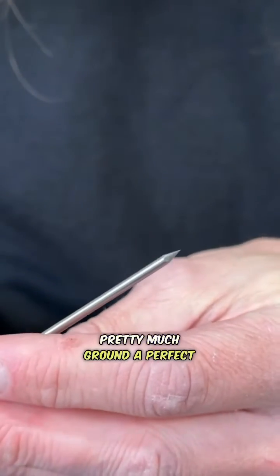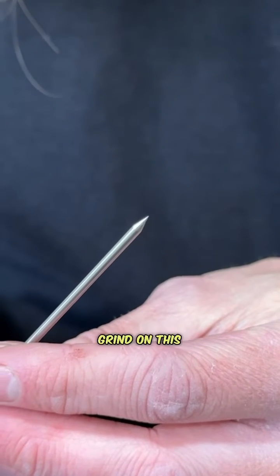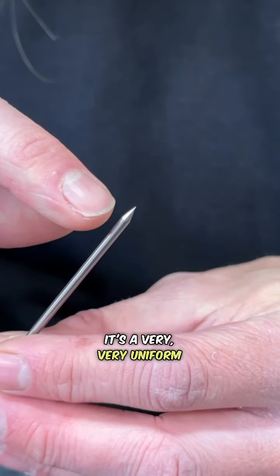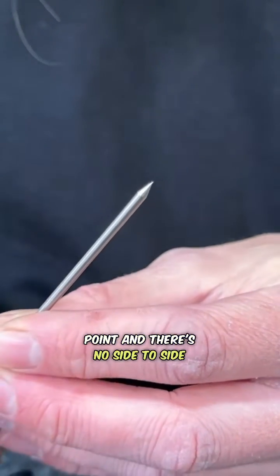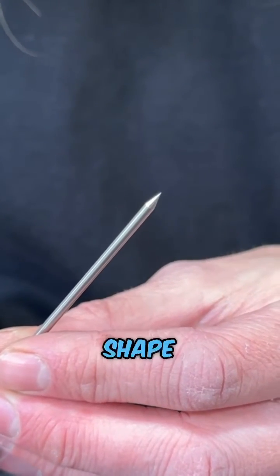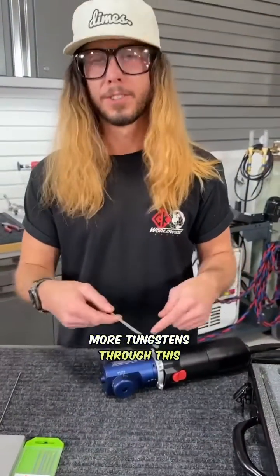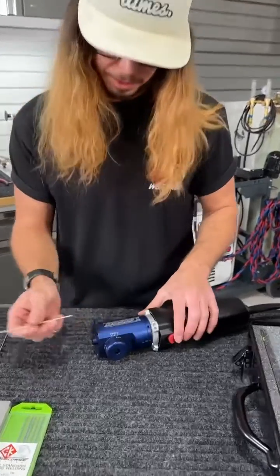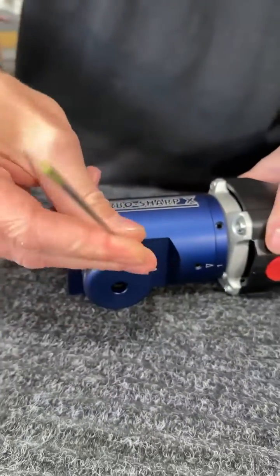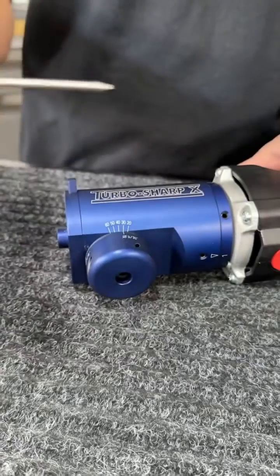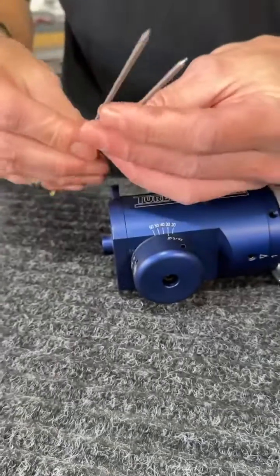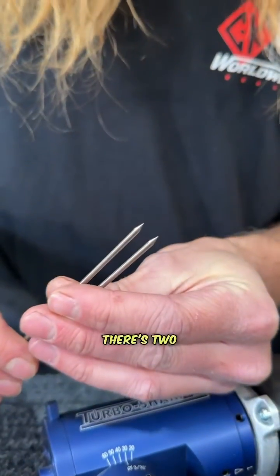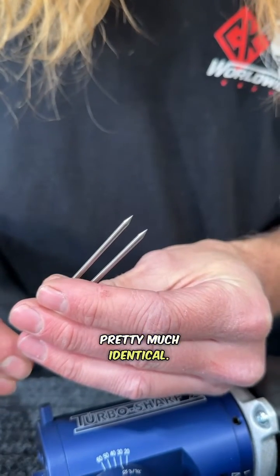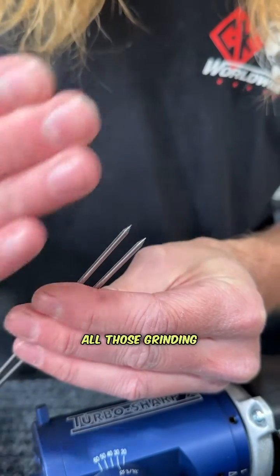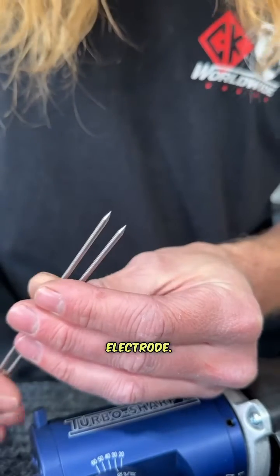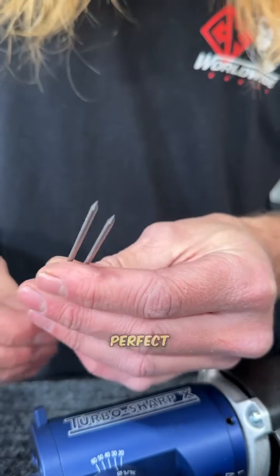Right here, you can see I pretty much ground a perfect grind on this end of this electrode. It's a very, very uniform point, and there's no side-to-side variation, and we basically have a perfect shape cone. We're going to put a couple more tungsten through this grinder and just show you how repeatable this is. So there's two electrode grinds, pretty much identical. There's not really any flat spots. All those grinding striations are running lengthwise through the electrode. And it's quite literally a perfect electrode grind.